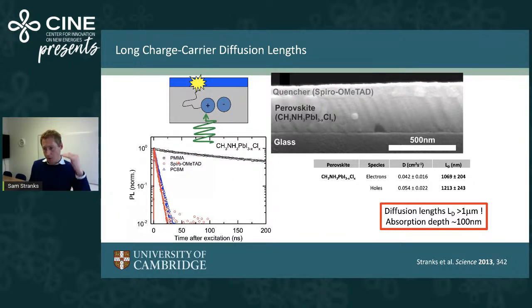We can then have another configuration where we put on an electrode, a selective electrode for one of these charges, either electrons or holes, and that quenches the luminescence. It makes the luminescence a lot faster because these charges now can hit these electrodes and be removed from the system. And so we can model that globally. We can think about a diffusion model that accounts for these charges moving around and also accounts for these charges being quenched.